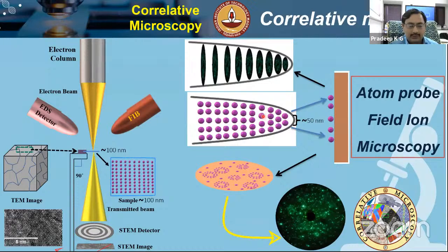Then one can definitely say that the deuterium that we charged is really coming from the material, and we will be able to identify its position in 3 dimensions. So one can say whether deuterium is really going to the defect site or is just dissolved in the matrix. So at least we can get a first-hand fingerprint of what this deuterium is doing, not exactly hydrogen, but of course the same family. So we can understand a little bit better than not having the information.